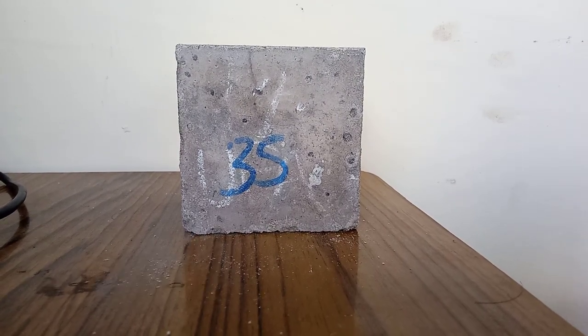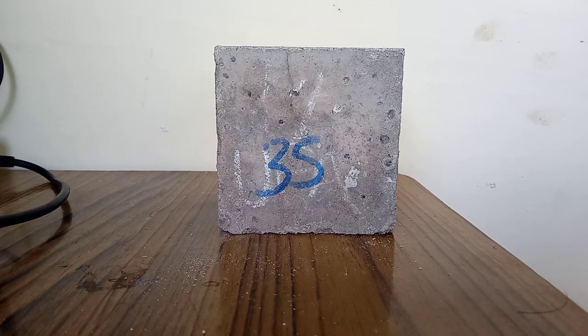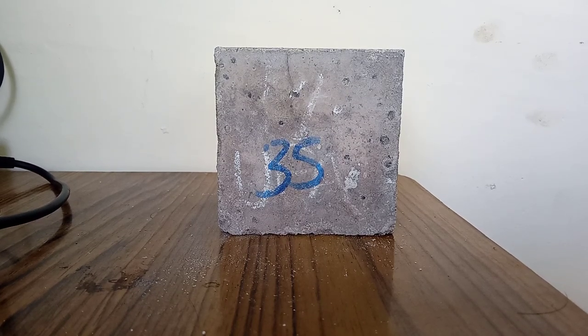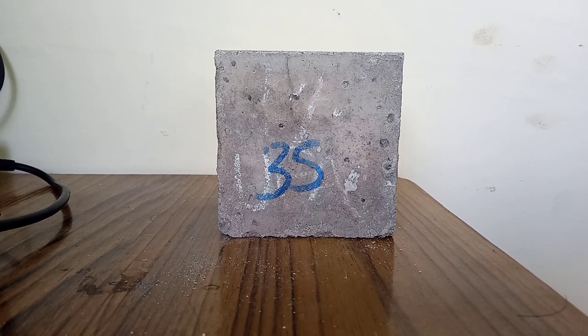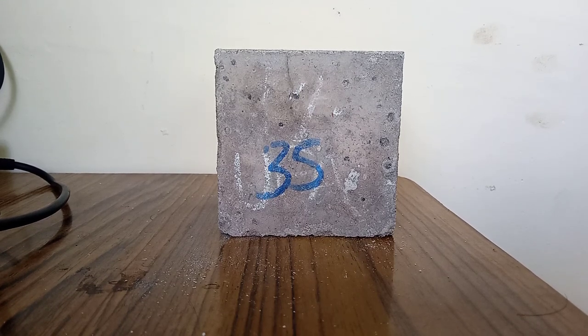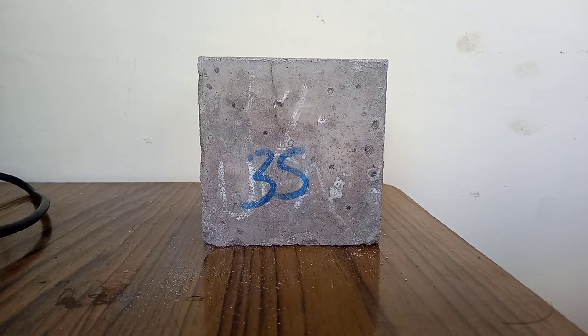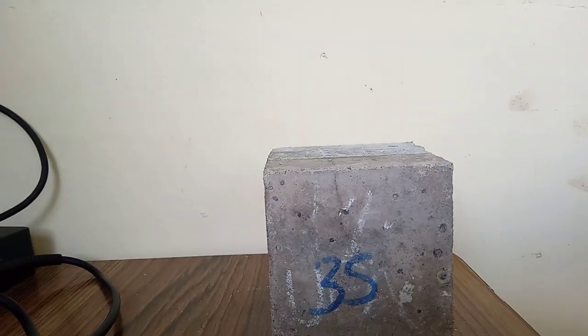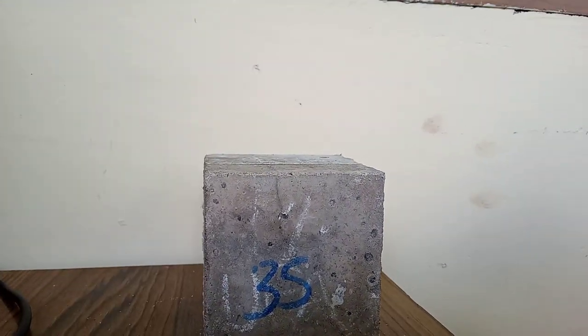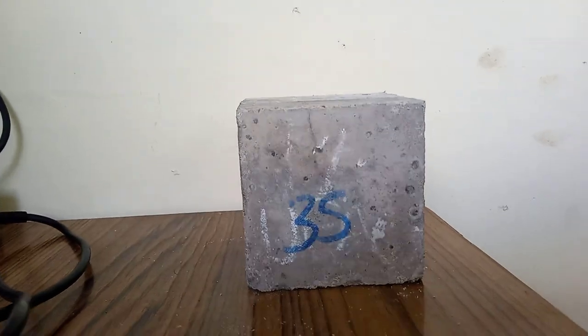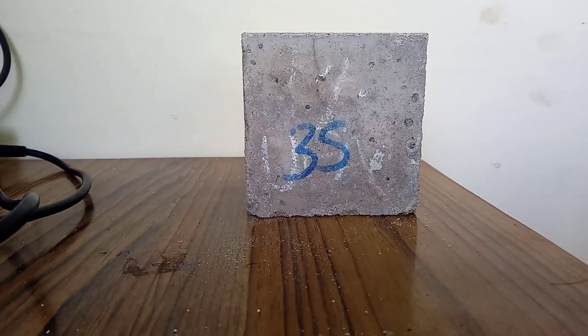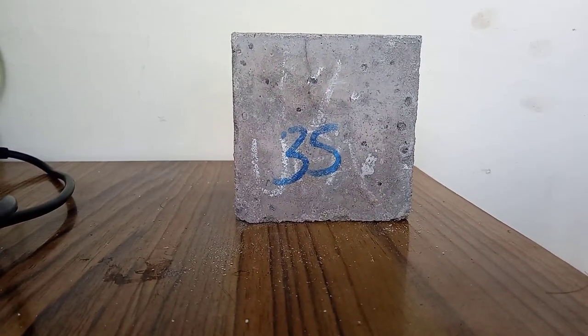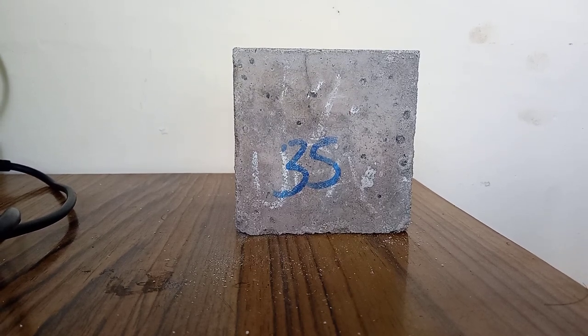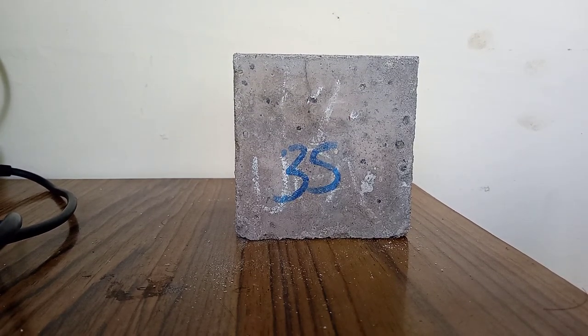In this study, the bagasse ash is chosen as the biomass ash. The sugarcane bagasse ash is used to partially replace the fly ash in the preparation of eco-friendly geopolymer concrete. For that, initially, the mortar study was carried out by replacing 0 to 20% by weight of fly ash by SCBA. From the compressive strength results of the mortar studies, the optimum percentage of replacement is finalized as 10% by weight of SCBA. By using the optimized percentage of SCBA, the geopolymer concrete was developed.